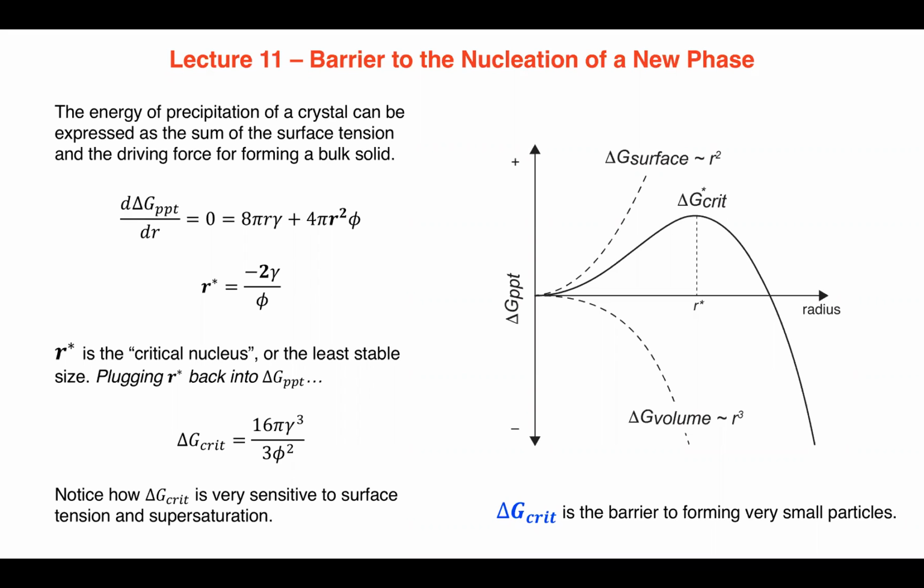Ethan? Wait, so just to clarify, is what you're saying that each size along the path of growth is basically a lot longer lived than a transition state would be? Yes. Yeah, because there are also going to be kinetic barriers to growing or dissolving a size. So you could make this R star and put it in solution and it would live for a while because there has to be some kinetic process to attaching to it or dissolving it. So each one of these, each point along this line, is actually a minimum.